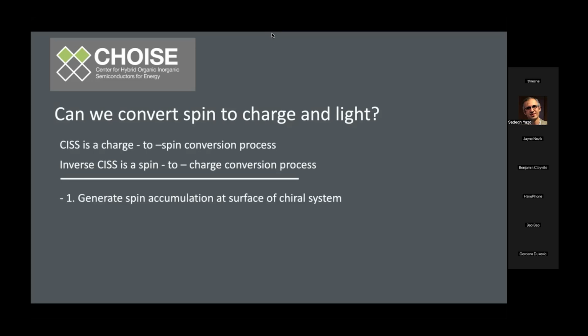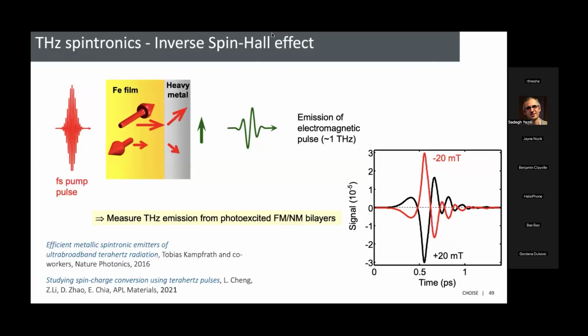All right. So to do this, we have to generate spin accumulation at the surface of the chiral system, and then we have to be able to measure the charge current that may be induced. So we're going to use the terahertz spintronics field. The basic idea is this. Let's say this is a ferromagnet. You have a femtosecond laser pulse that hits the ferromagnet. It heats it up. You have a spin Seebeck effect. It drives spin current in this direction over here, and then you inject that spin into, say, a proximal heavy metal, which undergoes the inverse spin Hall effect and generates a charge current that's perpendicular to the spin current. And then, since this is ultrafast, you read that out using terahertz spectroscopy.